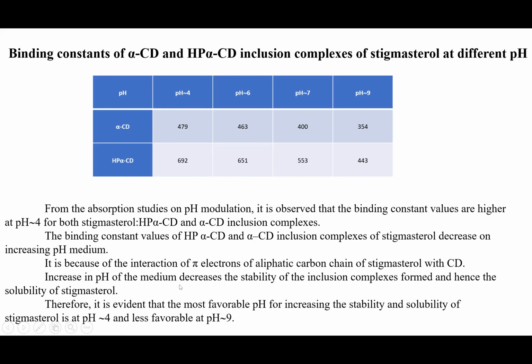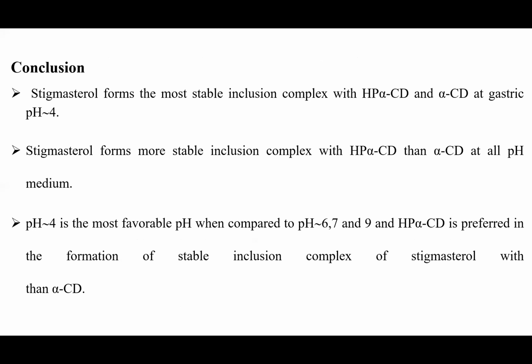Therefore, it is evident that the most favorable pH for increasing the stability and solubility of stigmasterol is pH 4 and less favorable at pH 9. So as a conclusion, stigmasterol forms the most stable complex with HP alpha CD than alpha CD, and it is at pH 4. pH 4 is the most favorable pH when compared to pH 6, 7, 9, and HP alpha CD is preferred over alpha CD in the formation of stable inclusion complexes of stigmasterol. Thank you.